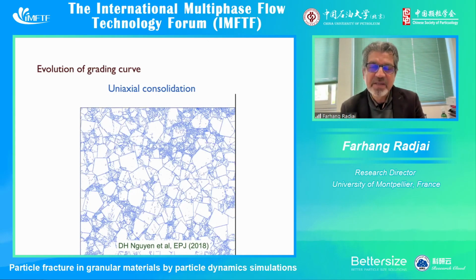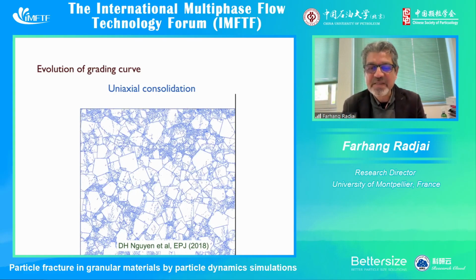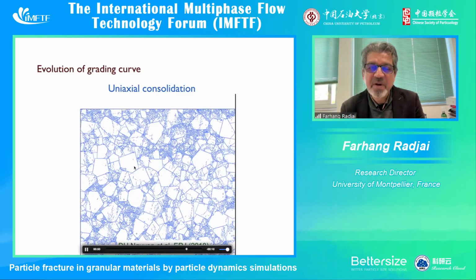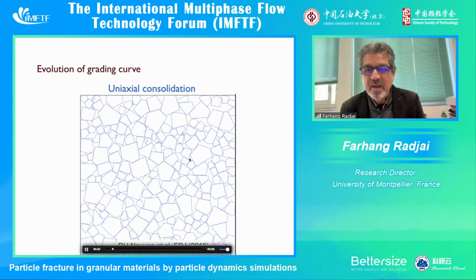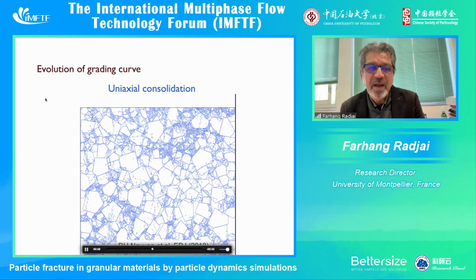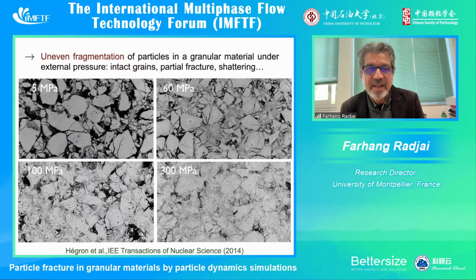And when we apply this method, we find features which are very similar to what we see in experiments. For example, here we see that due to the cushioning effect, most particles do not break. Many particles are only slightly damaged in uniaxial compaction. But we have shattering. So there are many places where we have particles which are fully broken. This is very similar, for example, to what we see here. So this is nuclear fuel, UO2, uranium dioxide. And as the pressure is increasing, at the beginning you have fracture of a number of particles. Then we have shattering at some places. And as the confining pressure is increasing, we still have particles which are not fully broken. So we have this rather complex behavior.